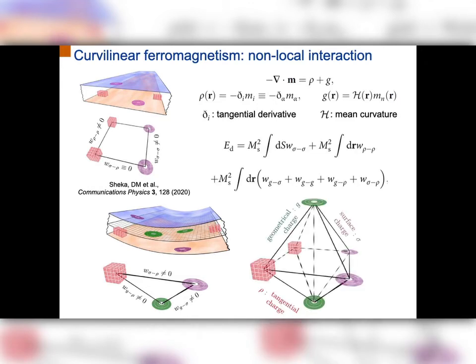In this case, you can write the non-local interaction in your system in a way that you will have not only standard surface and tangential charges interacting with each other, but also additional interaction between surface and tangential charge and volume, tangential and geometrical charge, which cause very interesting chiral symmetry break in the system.